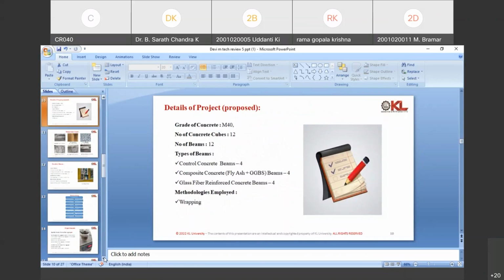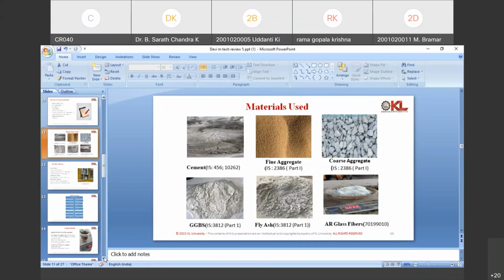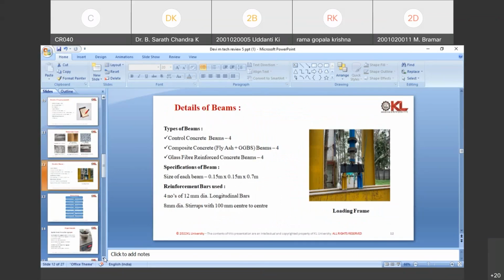These are the details of the project. Grade of concrete is M40. Number of concrete cubes is 12. Beams is 12. Type of beams: 4 control concrete beams, 4 composite beams with fly ash plus GGBS, and 4 glass fiber reinforced concrete beams. Method used is wrapping. These materials are used: cement, fine aggregate, coarse aggregate, GGBS, fly ash, and glass fibers. Size of each beam is 0.15 meters by 0.15 meters by 0.7 meters.